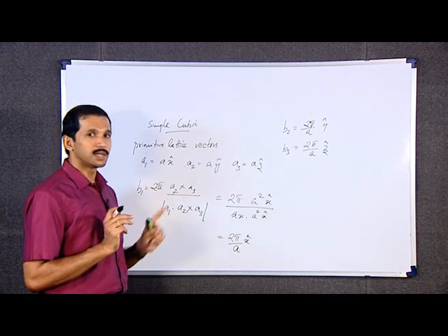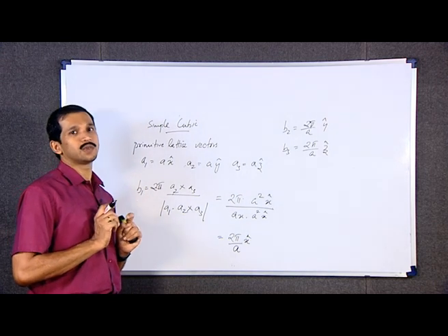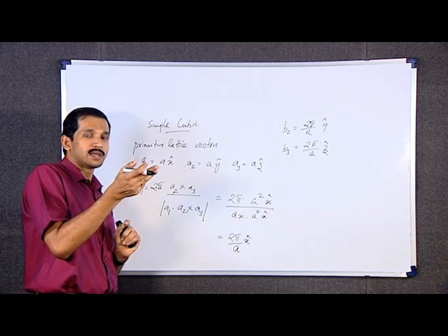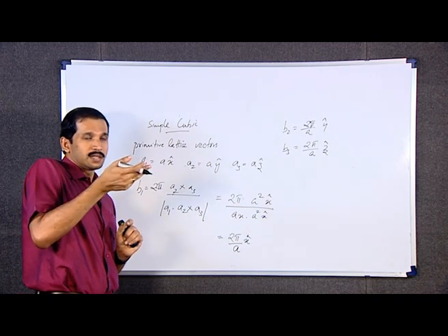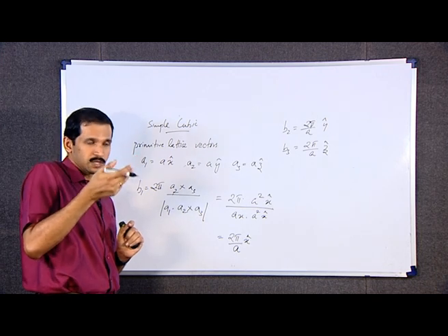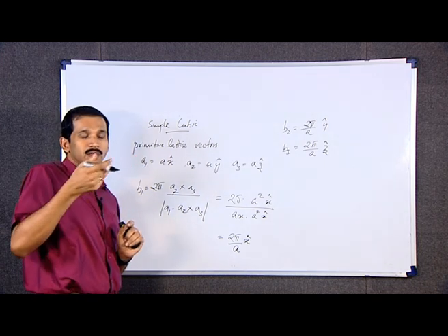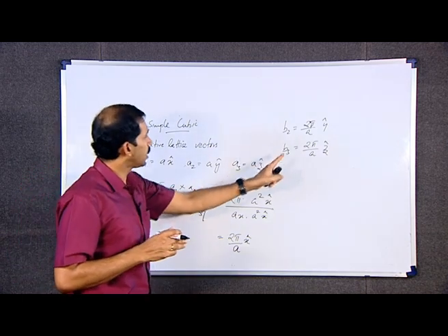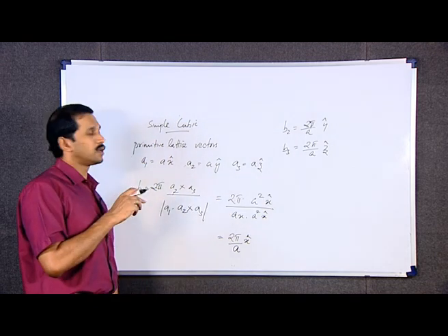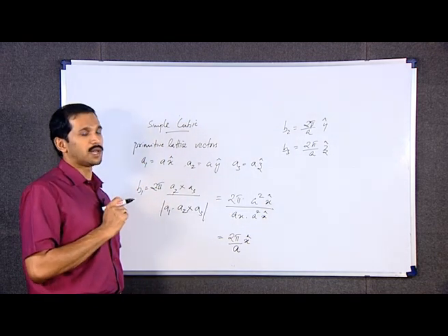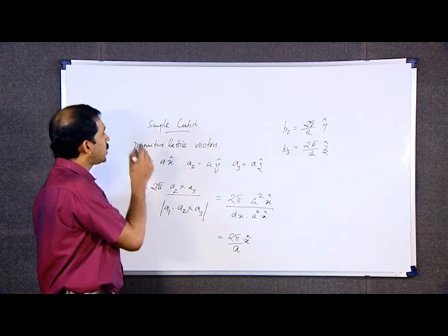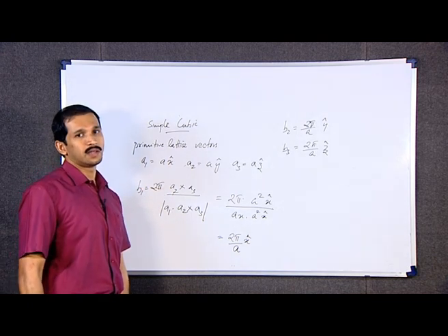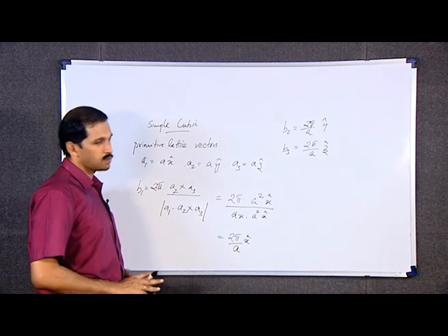When I described the reciprocal lattice vector, we already put in a hint that the higher the volume of the direct lattice, the smaller the volume will be in the reciprocal lattice. Similarly, the higher the a, the smaller the dimensions of the reciprocal lattice vector. So, the reciprocal lattice of a simple cubic is again a simple cubic lattice itself. That is the first evaluation.